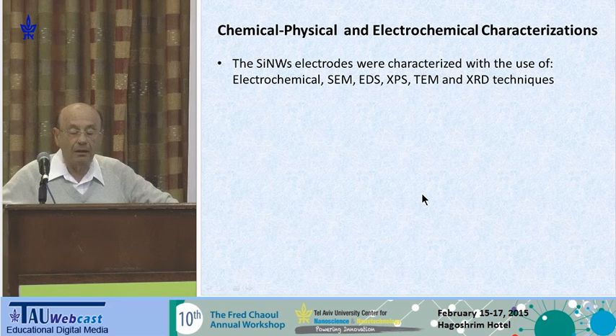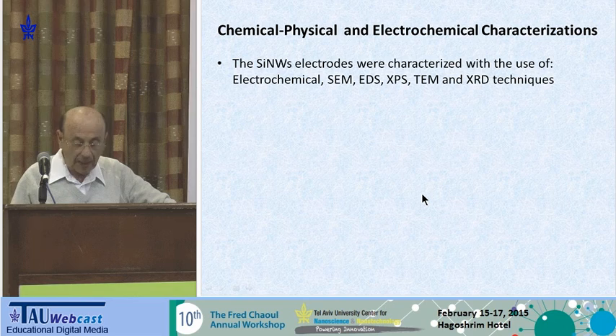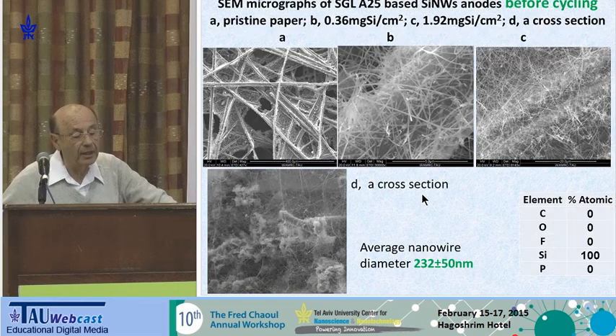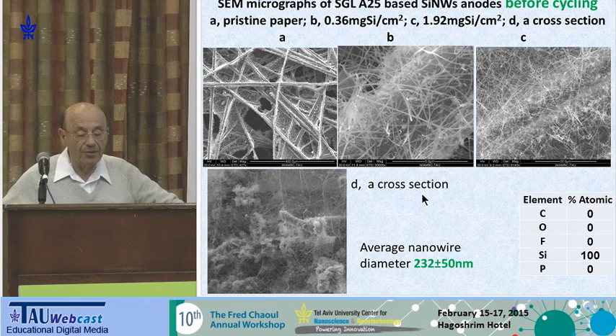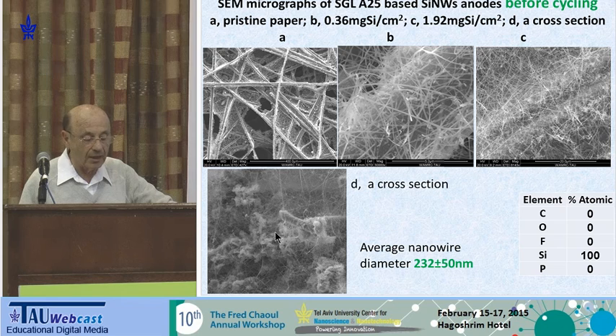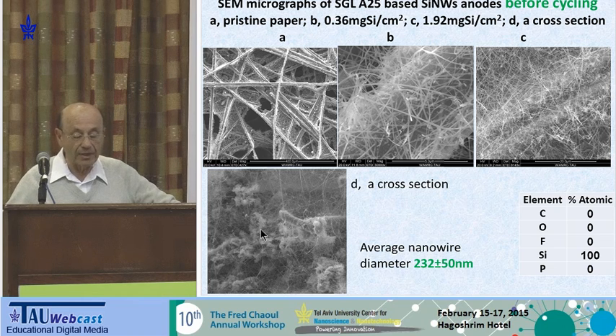And we analyze, characterize this anode by different means. And what you see here on A is a micrograph of the carbon paper. It is made of fibers about 6 or 7 micron thick. And B is the deposition or growth of silicon nanowires on this carbon paper. But most importantly is the D micrograph. Here you see the carbon fiber, and you see a lot of wires inside. So this is a cross-section of the paper, and you see that we can deposit silicon nanowires into the paper and therefore utilize the full capacity or the full volume of the substrate.